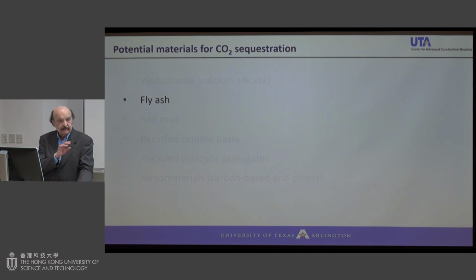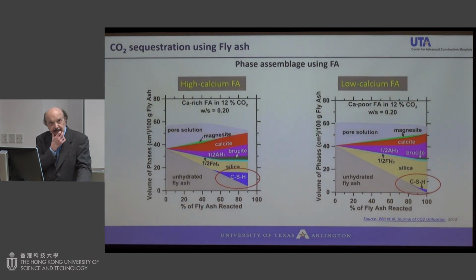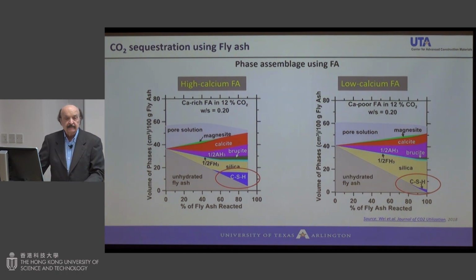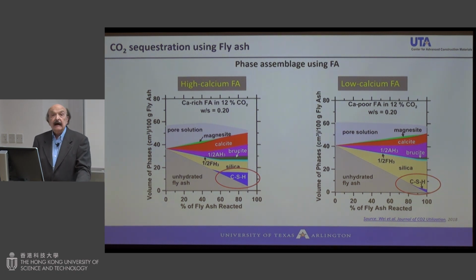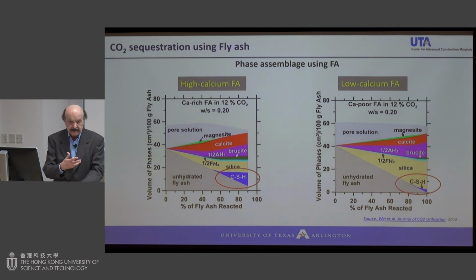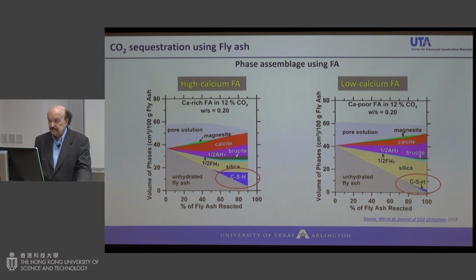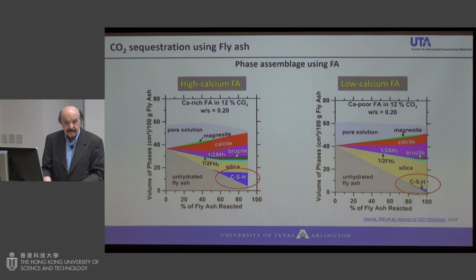So now we talked about wollastonite. As I mentioned, it's commercialized, and we can manipulate wollastonite to increase the amorphous content. Fly ash: most of the time when we use pozzolanic material, we are talking about low calcium fly ash, often called class F in the US. High calcium fly ash is normally not preferred because there is high CaO, calcium oxide. But for carbonation, if you have a low calcium fly ash, then the calcium is used by carbonation. As a result, the pozzolanic reaction is less, and you have only a small amount of CSH. So that's not preferred for carbonation. For carbonation, we prefer high calcium because you have enough calcium for both carbonation and the pozzolanic reaction.